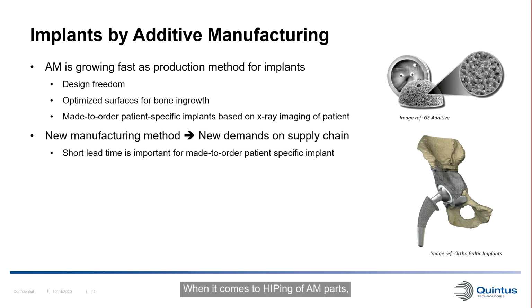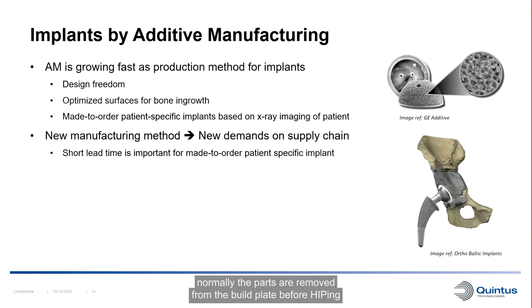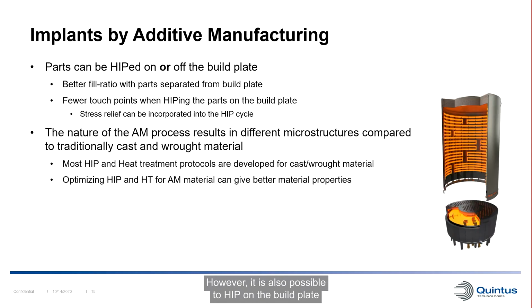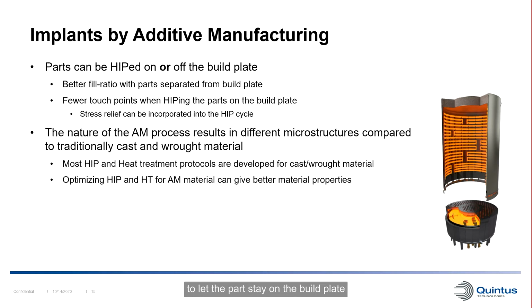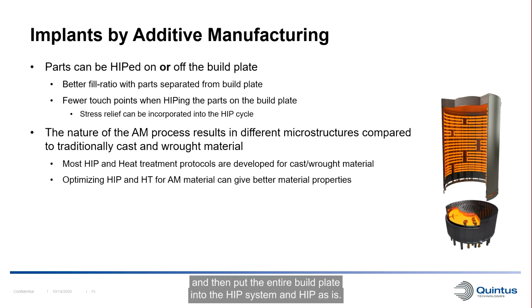When it comes to hipping of AM parts, normally the parts are removed from the build plate before hipping, and you place these implants into the HIP furnace separately. However, it is also possible to HIP on the build plate, to let the parts stay on the build plate and then put the entire build plate into the HIP system and HIP as is. By removing the parts from the build plate, it's possible to get a better fill ratio in the HIP. But by loading the entire build plate into the HIP system, you can normally reduce the number of touches in the process, so you can run the whole thermal processing of the build plate and the parts, and then take the parts off the build plate in the end.